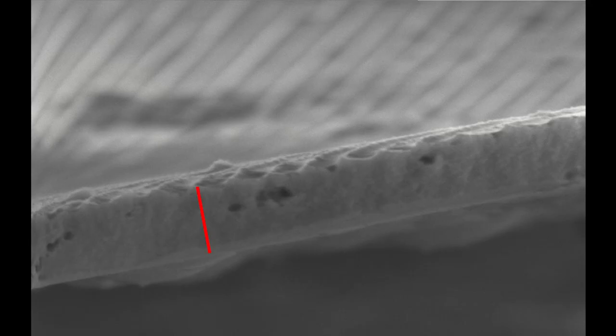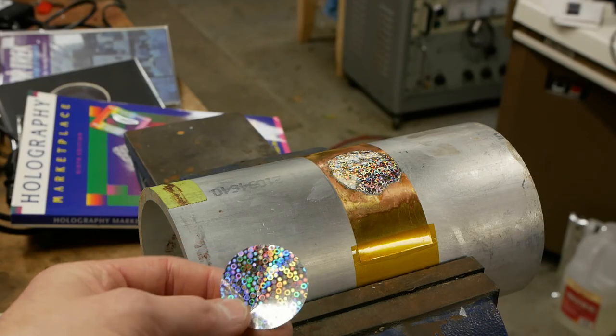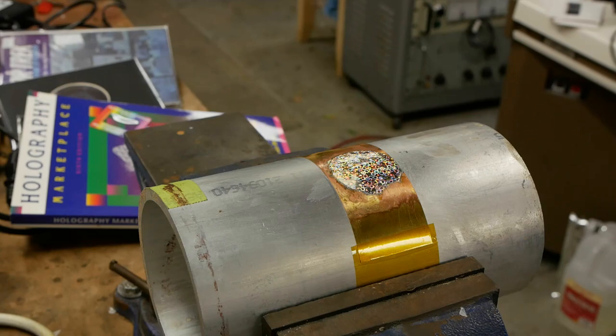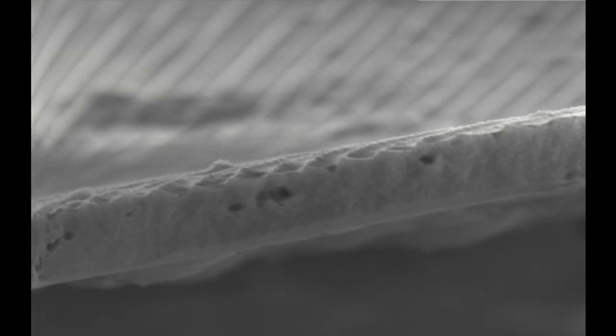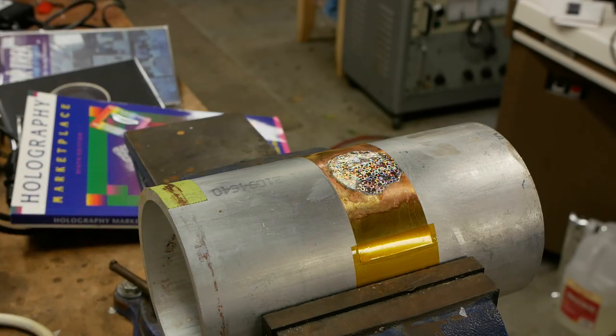So the whole sheet thickness is probably on the order of 20 to 30 micron. And if we use that as kind of a yardstick, we can figure out the peak-to-peak spacing of this diffraction grating is surprisingly big. It's maybe about 10 or 15 micron. I suspect for very simple patterns like this sticker, the diffraction grating can be pretty far apart, even as far as maybe 10 micron, I guess, even though that does seem high. But some of the gratings for the holograms are probably much tighter, more like 1 micron. And if you look closely, you can actually see another surface texture that's superimposed on the large ridges. And I suspect that the diffraction grating might actually be those tiny ridges. And the large ones are just, I don't know, different surface modulation or something. I'm not really sure exactly how the patterns for these are created. They may not be created optically like a hologram would be created from raw materials.